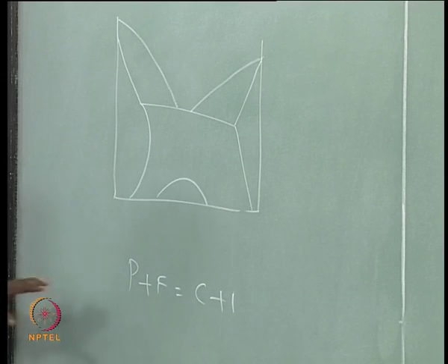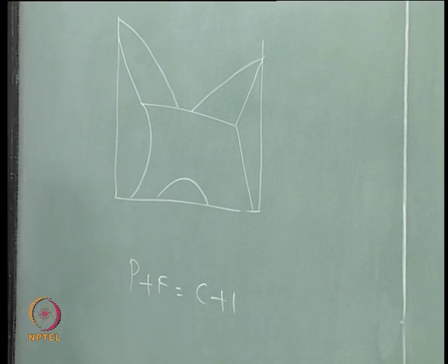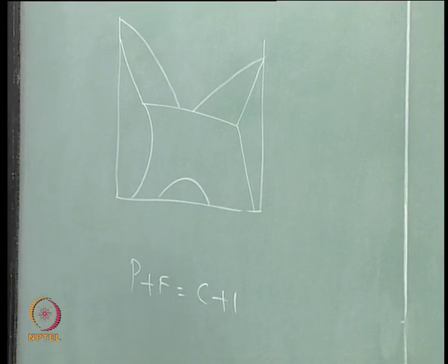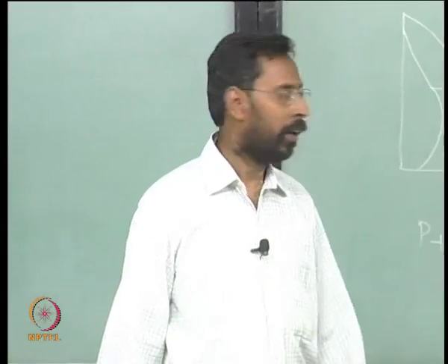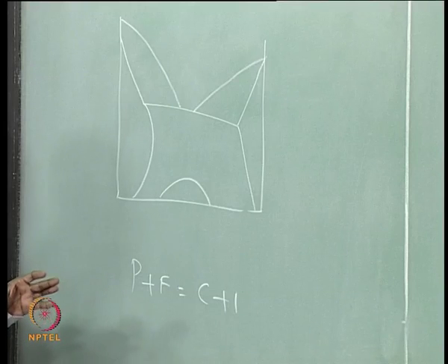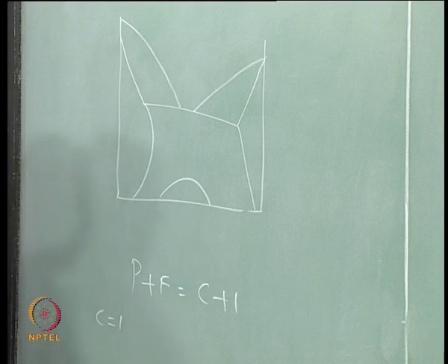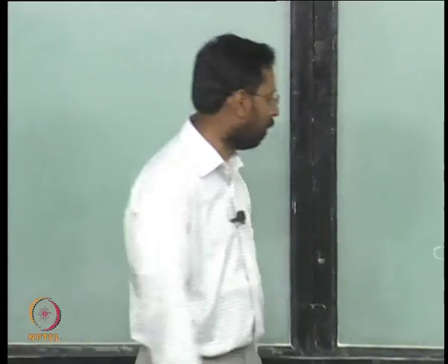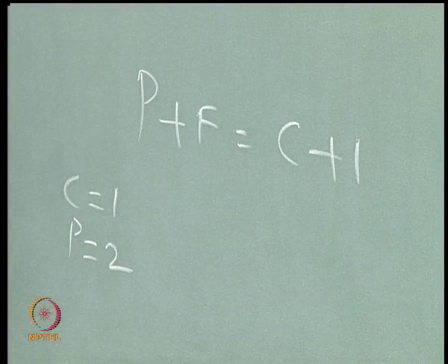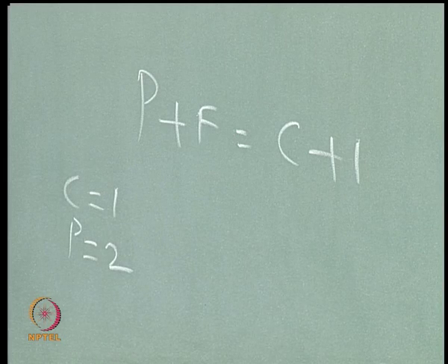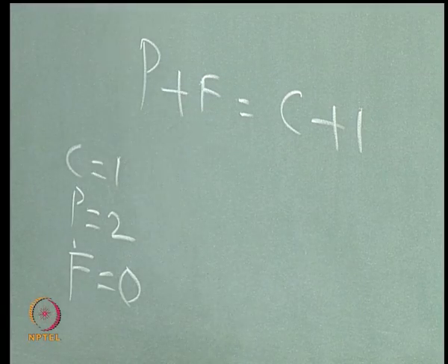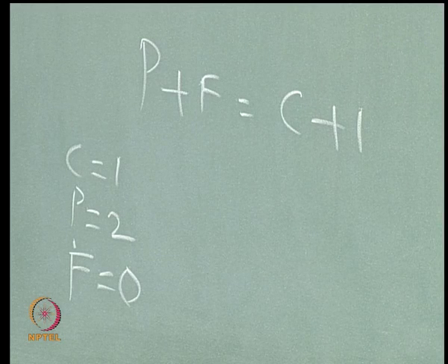As a result, you can see that this phase rule tells us that whenever you have a transformation taking place at the pure metal end, where the number of components is equal to 1, then the phase transformation should deal with 0 degrees of freedom. Because if C is equal to 1, and there is a phase transformation where one phase is transforming to another phase, P becomes equal to 2, and the moment C is 1 and P is 2, automatically F is to be equal to 0. So that is what that phase rule tells you. So the degrees of freedom for any phase transformation for a pure metal, where